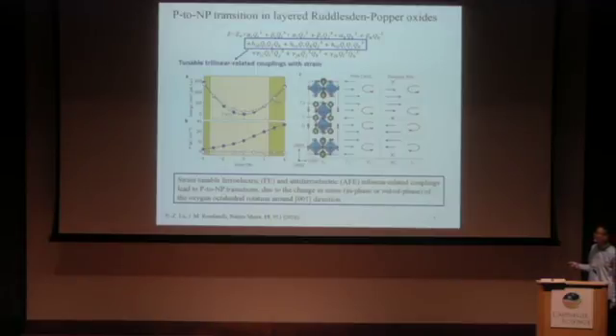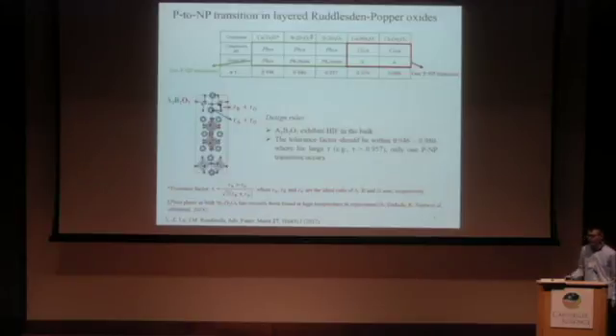But as studied by the Landau model shown here, we found that the strain tunable trilinear couplings in the two phases can be responsible for the appearance of the nonpolar phase under epitaxial strain. To apply our theory to other compounds in the A3B2O7 family, we find more materials showing such unusual polar to nonpolar transition under epitaxial strain.